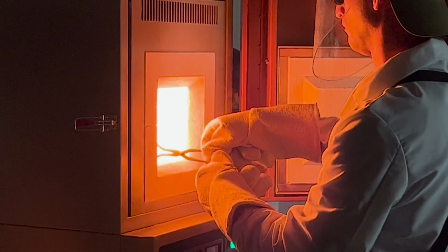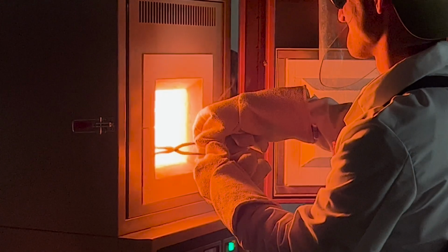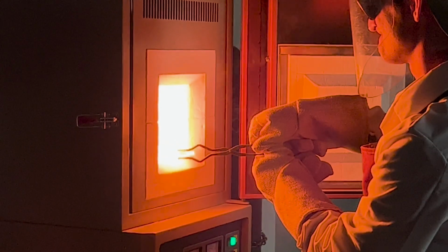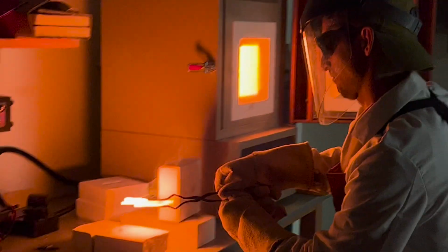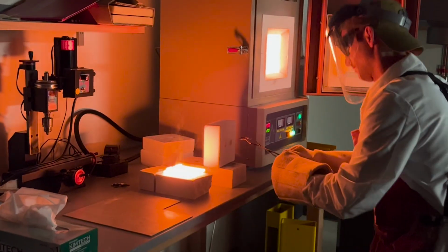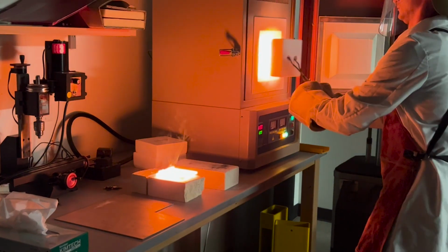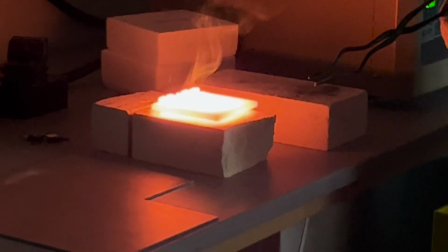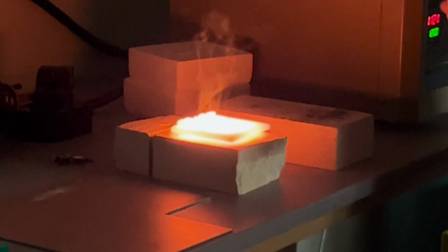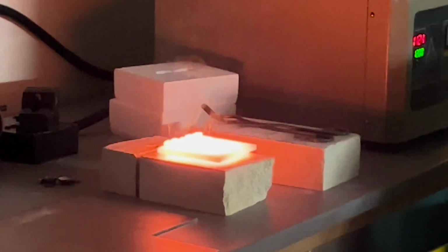We started at 1000 C, put all 7 compositions in there and then ramped it up another 100 degrees and started throwing compositions out as they failed. And one of our compositions just refused to die. We got it all the way up to 1600 C, and that's when we really realized we had something special going on with that composition.